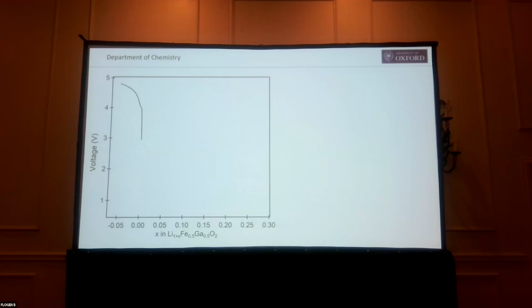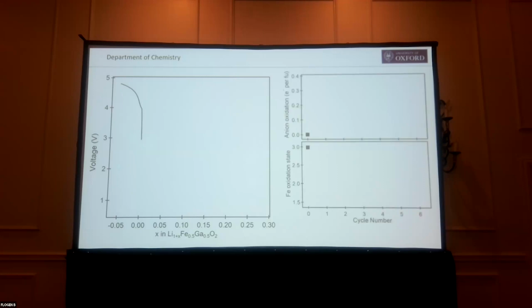So we start here with our lithium 1.0, and the first thing we do is an oxidation. We take out about 0.05 lithium per unit. And what we can do is keep track of the iron oxidation state, and how many electrons we think we've oxidized at the oxygen. In this first step, we don't actually oxidize any iron. It's all anion. So our iron oxidation state is 3, and we get about 0.05 electrons' worth of anion redox.